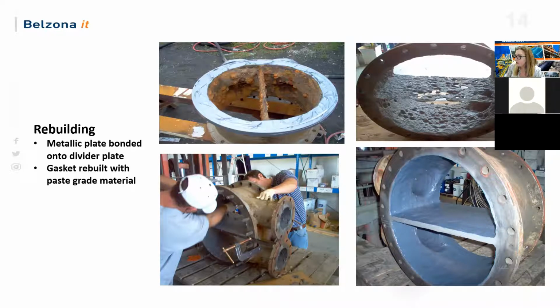So what we did was we reinforced the divider plate with a paste grade and remolded it back to the original integrity. And then we applied 2 coats of our protective corrosion protection. The asset owner wasn't able to get another piece of equipment for 6 months, but we were able to return this in 24 hours.